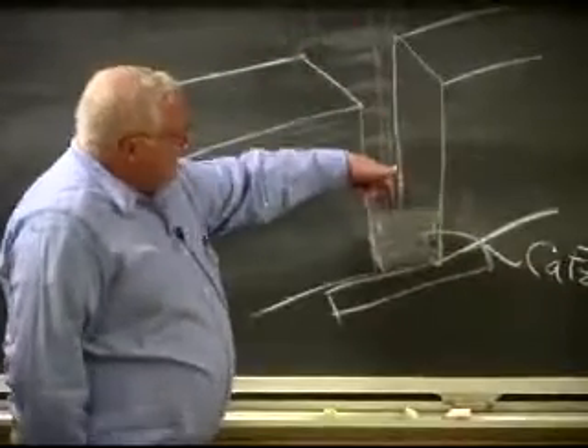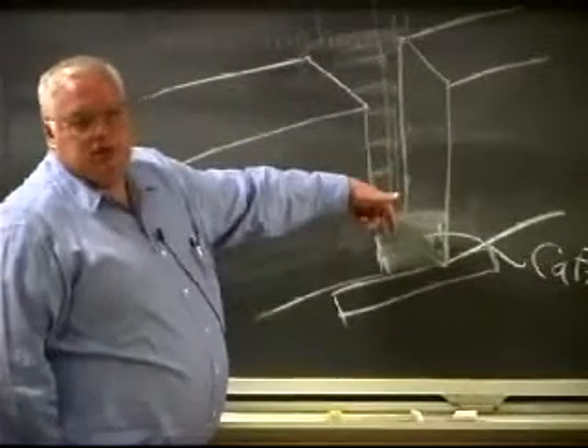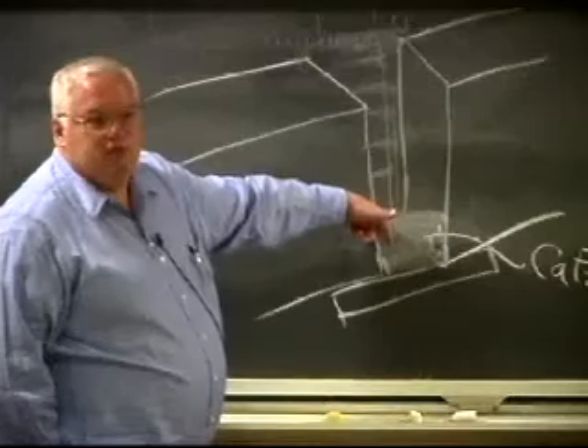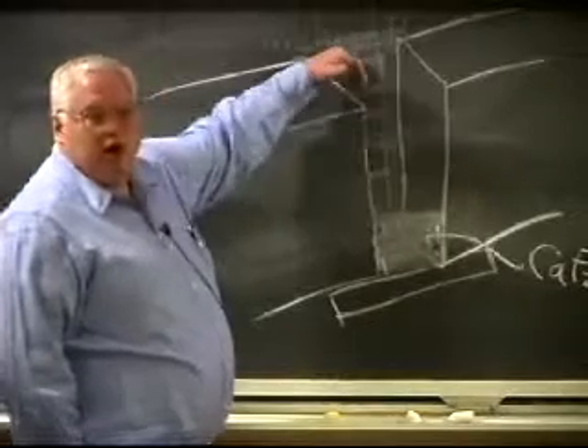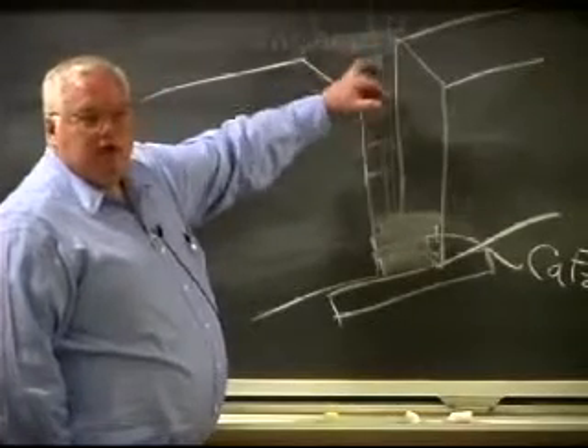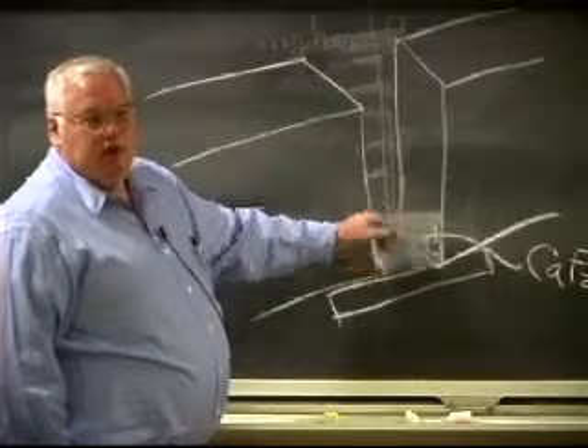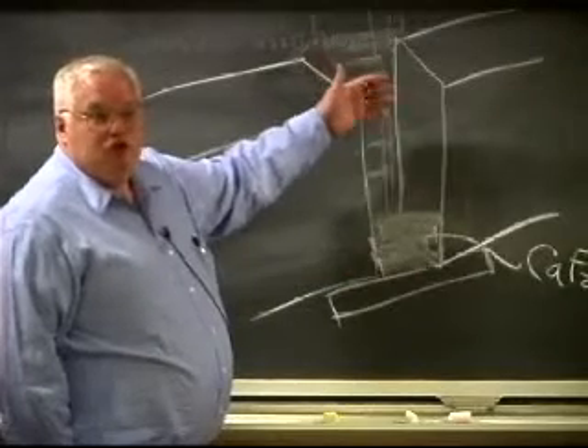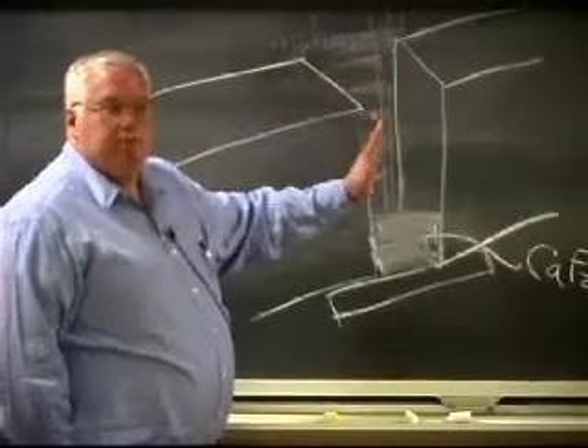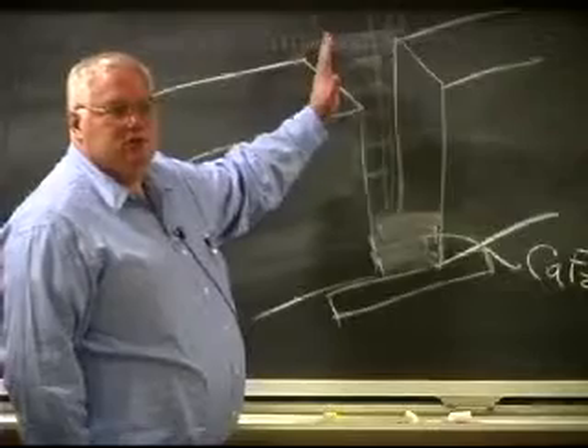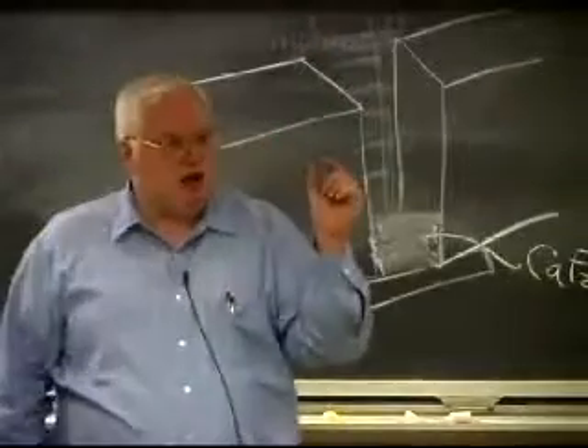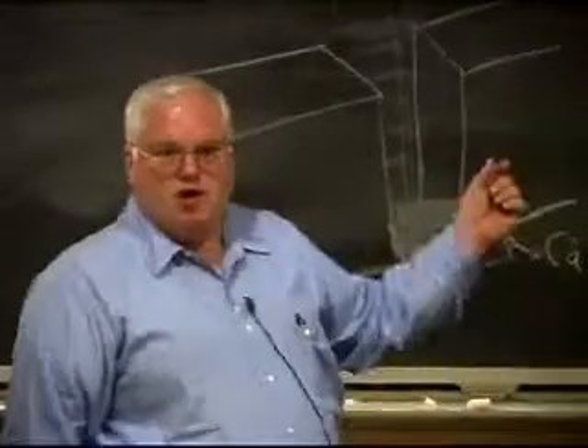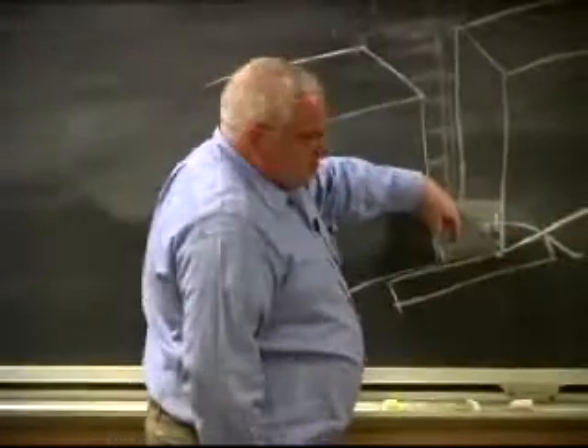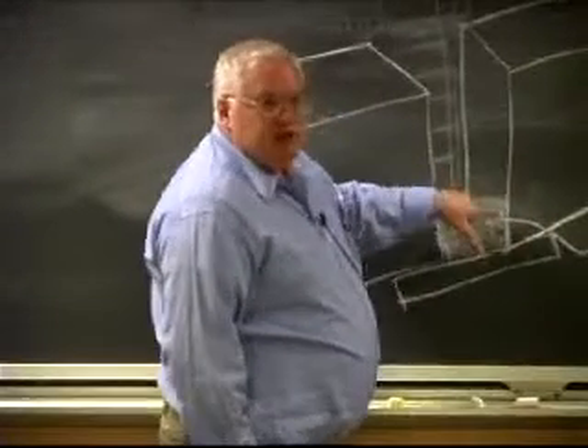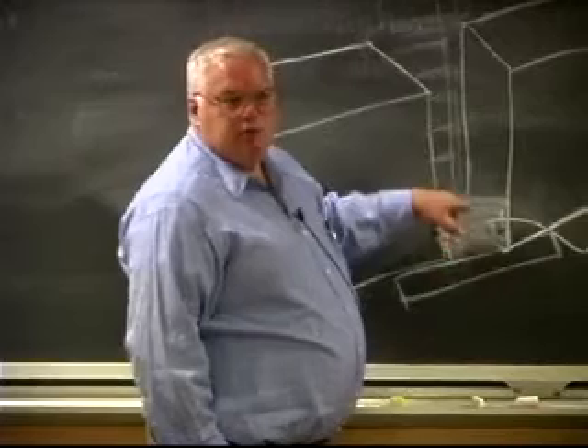I feed the wire in here while I'm continuing to pass 1,000 amps, 2,000 amps. If I'm doing a 1-inch plate or a 2-inch plate, I may have 1 wire feeding in here. If I'm doing a 3 or 4 or 5-inch plate, or people have done 10-inch plates, you have multiple wires going across. You still only keep the gap about an inch, inch and a half, but you basically make it a long, narrow weld. The wire feeds in, and it resistively heats. There's no arc except to start the process.